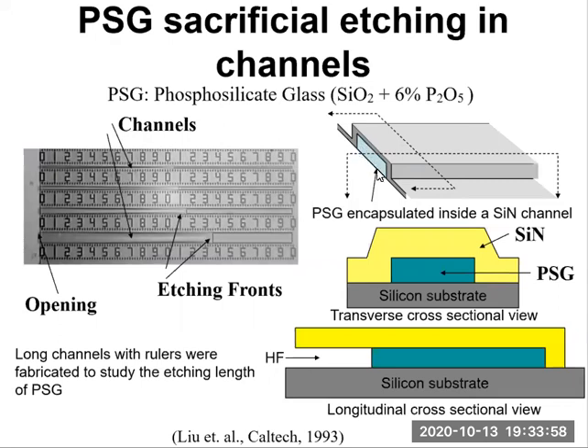Then the channel is opened at one end. For example, in this case, it's the left end. Then we immerse the chip in HF solution. So PSG is etched by HF. This is the picture taken under the microscope. Under the microscope, we can measure the etching length as a function of time. We know that the microchannels are opened on the left end.